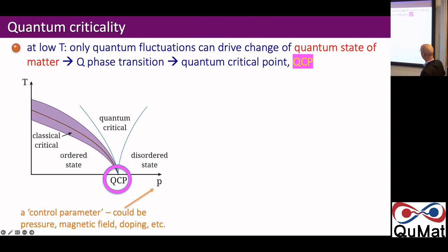But these kinds of systems, for example, in a cartoon sketch, you could have temperature against some knob you have, let's say pressure, magnetic field, doping. Let's imagine you go from some ordered state to some disordered state. And if you do this at very low temperature, there are no thermal fluctuations and only quantum fluctuations available to drive this change in the state of matter. So we call this kind of point a quantum critical point. And luckily for experimentalists like me and the others here, you don't have to get to absolute zero to see the consequences of this. There's a kind of tornado funnel of quantum critical behavior which sticks up to higher temperatures. I think certainly tens of Kelvin, maybe even many tens of Kelvin. So we can do experiments to look at that.